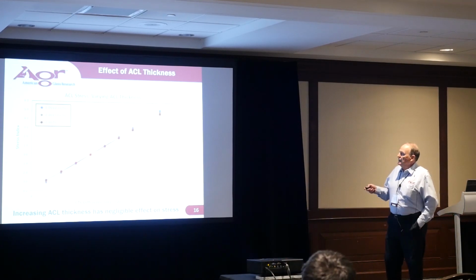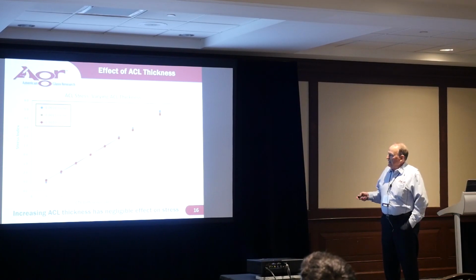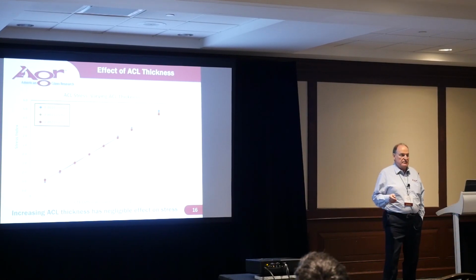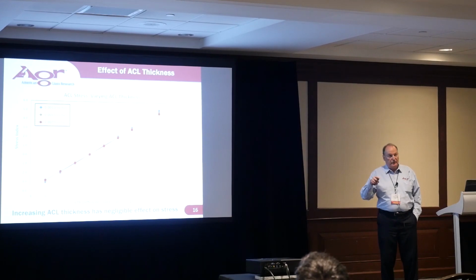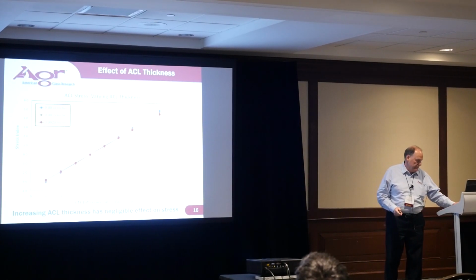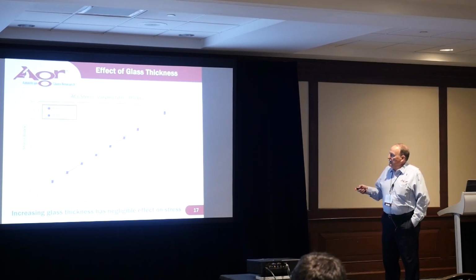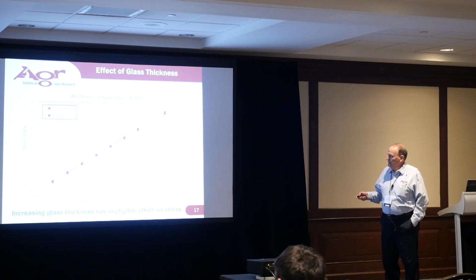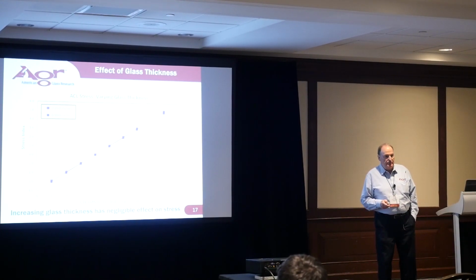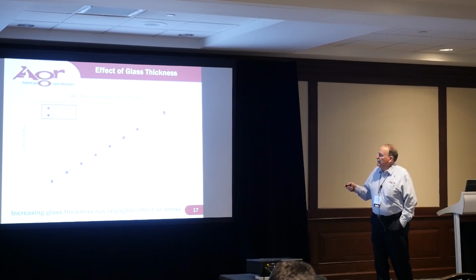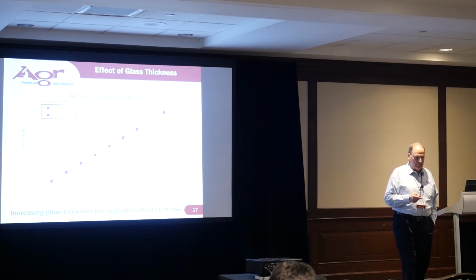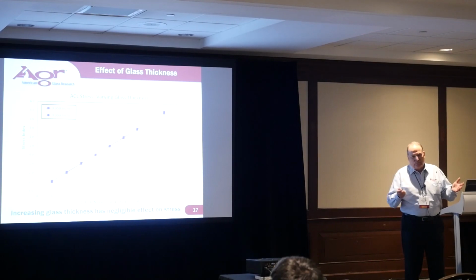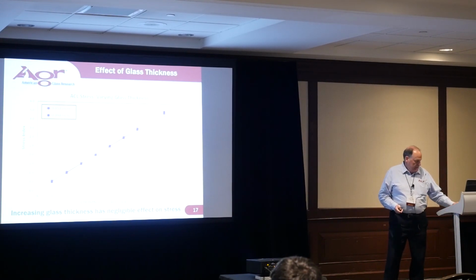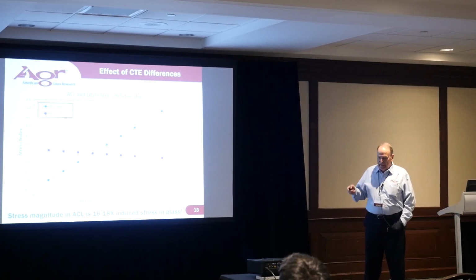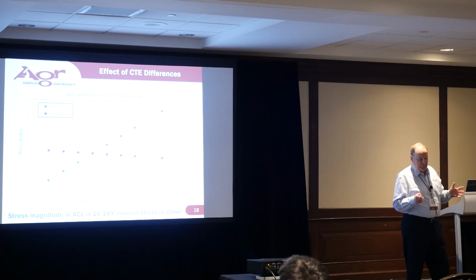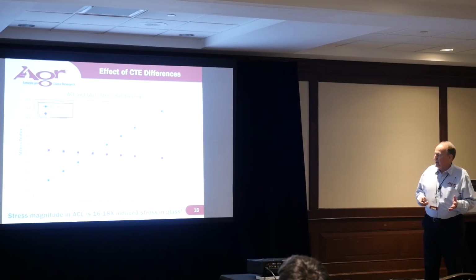Now this first plot, where we looked at the variation of the ACL, the data values here are for a glass thickness of 0.09 inches. When we looked at the data plot for 0.05 inches, it was the same. Likewise here, we were looking at the glass thickness effect. These data are for a glass thickness of 0.09, for an ACL thickness of 1.5 thousandths of an inch. When we looked at 1 and 2, it was the same. So what we did is, this is a composite of all of our glass thicknesses, both glass thicknesses, all three ACL thicknesses averaged together.